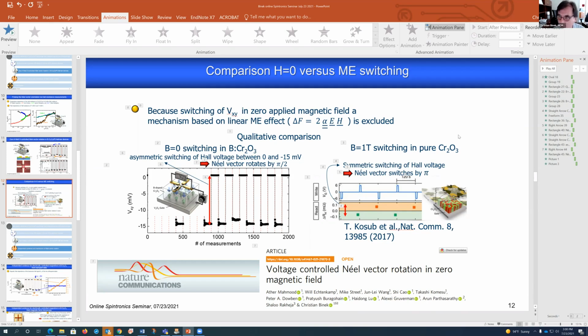And you can do that because you apply electric and magnetic field. That is without question, that is long known. That is known for 60 years or longer. So that's not a question, that happens. In our system, in the absence of an applied magnetic field, that would be hard to understand. And indeed, from what we observe and how we interpret it, we think that what happens is that it's not a 180 degree rotation here, but a 90 degree rotation of the order parameter and of the boundary magnetization.